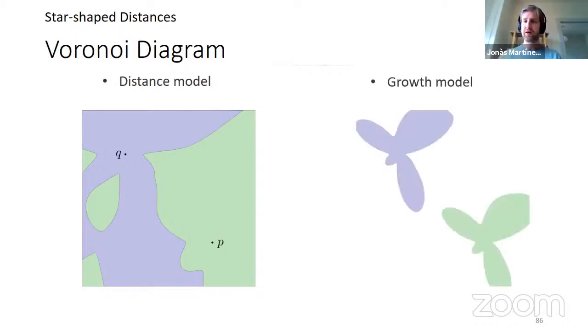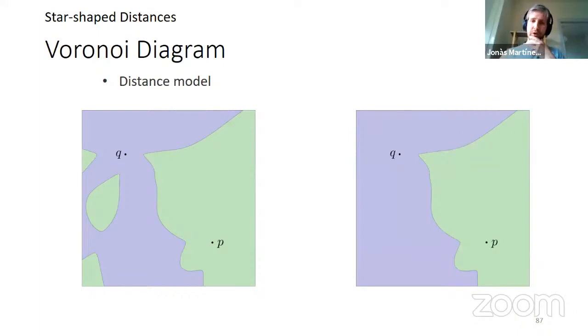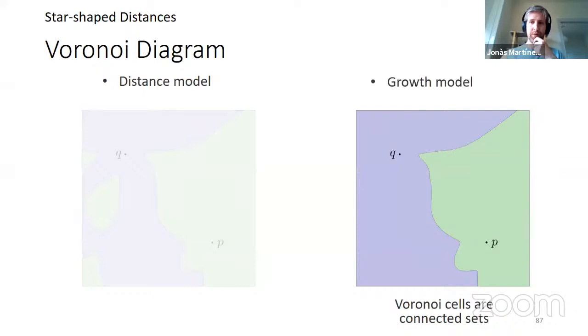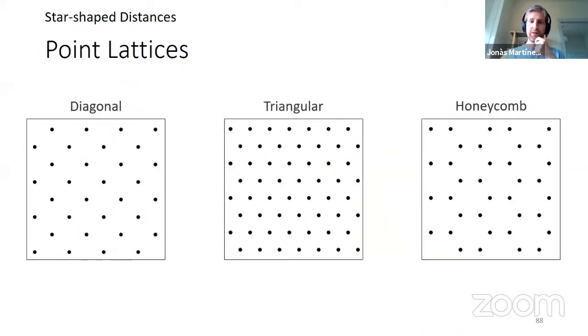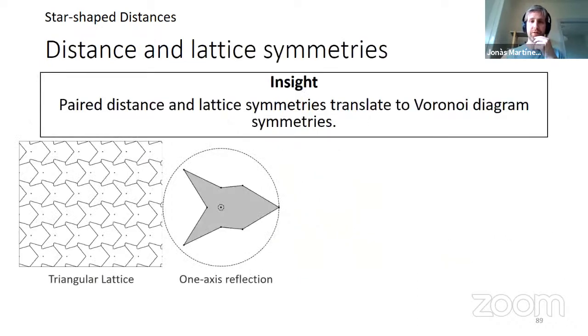We resort to another classical alternative formulation of Voronoi diagrams, which is the growth model, where basically you have your star-shaped set, and then the star scales in an isotropic fashion. Whenever and wherever it touches another cell, it stops scaling. So you start scaling, and then you get that. This is nice because by definition, your Voronoi cells now are a connected set by construction. And then the point lattices we consider in this work are three that are pretty standard in 2D: the diagonal, triangular, and honeycomb. But you could use other point lattices.